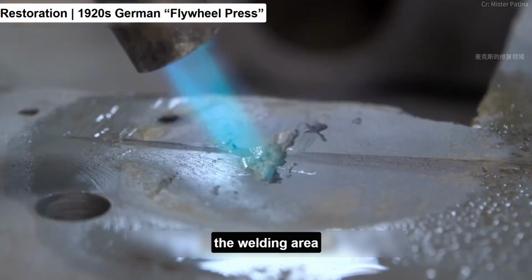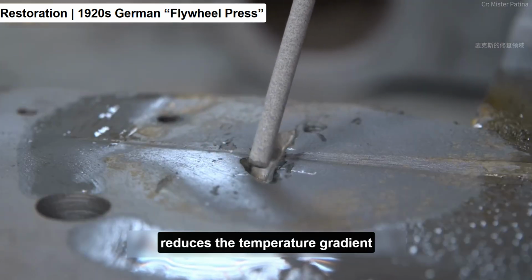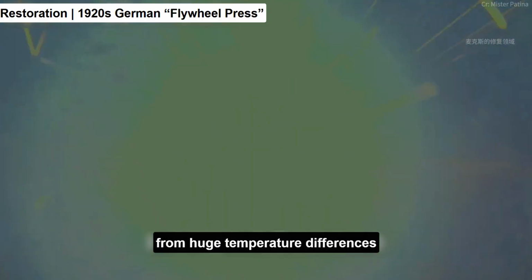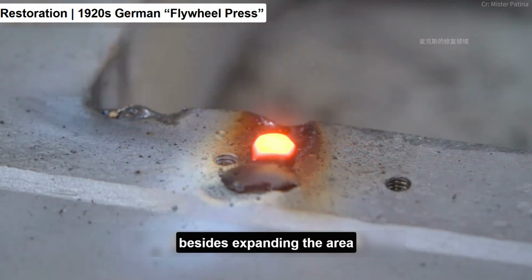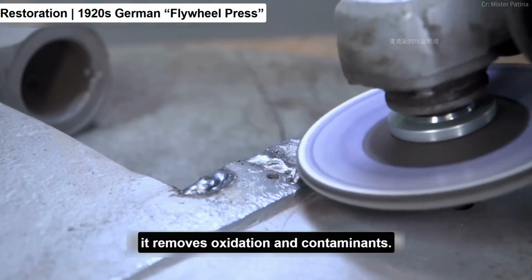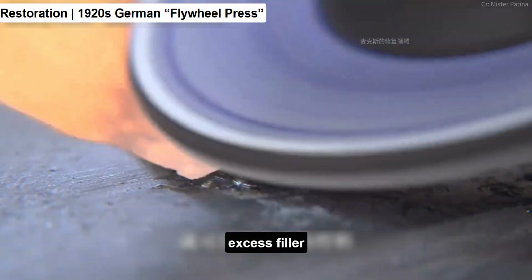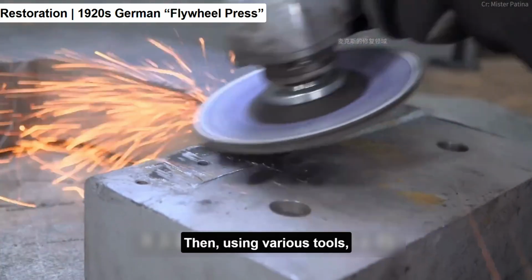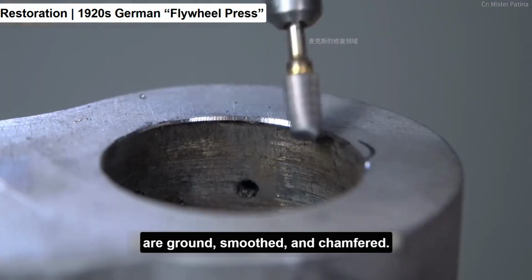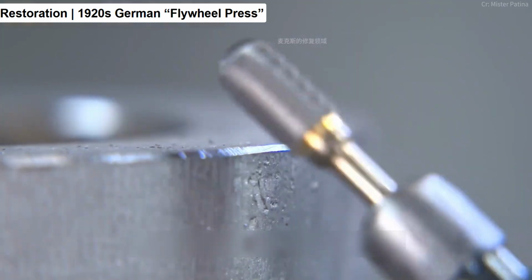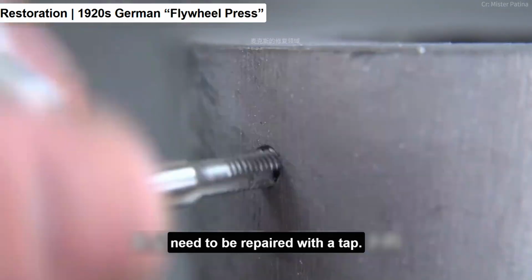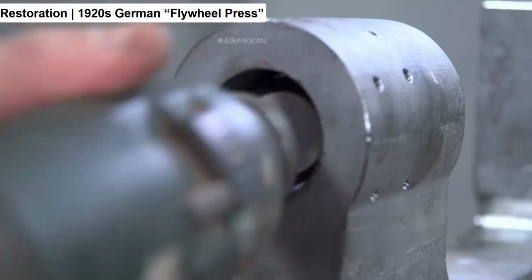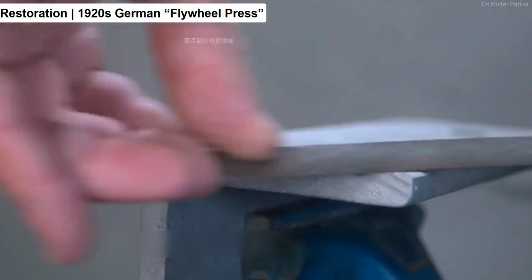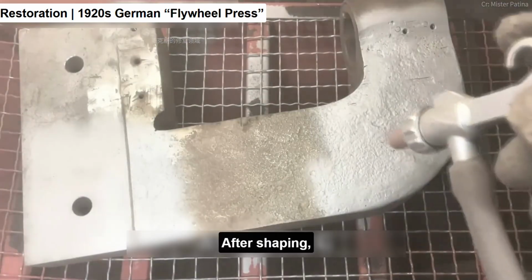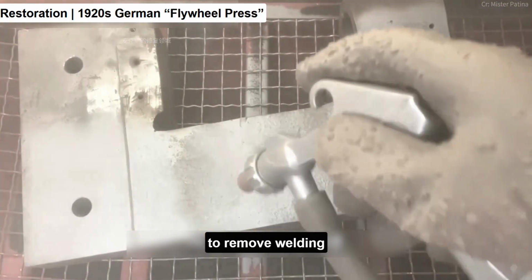Before welding, the welding area must be preheated. Preheating reduces the temperature gradient to avoid internal stress from huge temperature differences and the risk of cold cracks. As for grinding the surface, besides expanding the area for better bonding, it removes oxidation and contaminants. After welding, the excess filler can be ground away. Then, using various tools, these parts are ground, smoothed, and chamfered. Also, the threaded parts need to be repaired with a tap. After shaping, sandblast it again to remove welding oxidation marks.